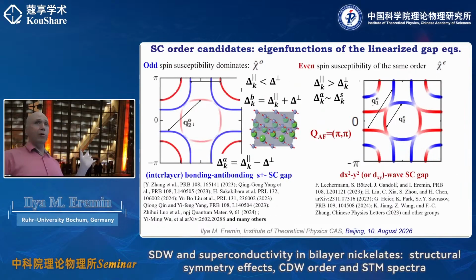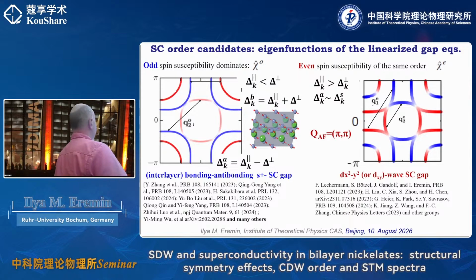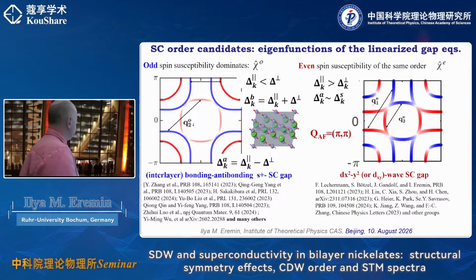And now again, that's a kind of introductory part. You ask yourself, okay, so what kind of pairing do I get? And then it turns out that depending on the methods, models, and so on, people get very different symmetries. I think if you start from the, let's say, itinerant perspective, what most likely you get is an s± symmetry. And that essentially in real space means that this is a pairing between the layers. So essentially, you have a superconducting gap where you really form pairs between the two layers. And in this case, if delta perp is larger than anything happening in the plane, and if you do this unitary transformation to symmetric and antisymmetric bases, then delta perp comes with a plus in the one and the minus in the other.